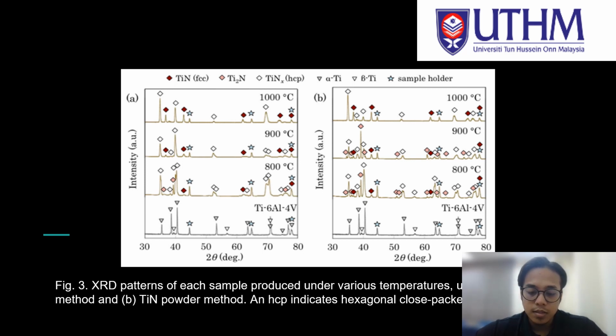On the other hand, the XRD exhibited TiNx and FCC titanium nitride phases existing at the 1000 Celsius process.